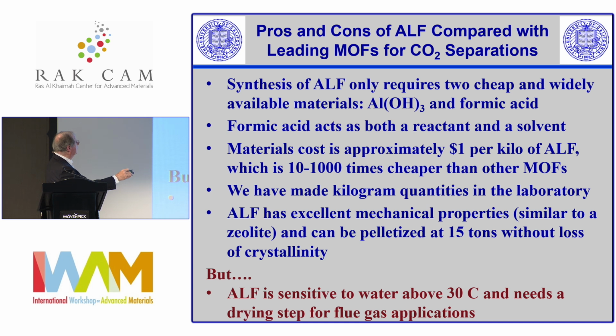And we can make kilogram quantities in the lab. It's very easy to scale up, at least in the lab. That doesn't mean you could do it in a large production facility. And it's got excellent mechanical properties. They're more similar to those of a zeolite in terms of the Young's modulus and the shear modulus. These were calculated numbers, but we measured the shear modulus of ZIF-8 once, and it's about 1, and this is 11 or 12. So it's dramatically better than most zeolites.